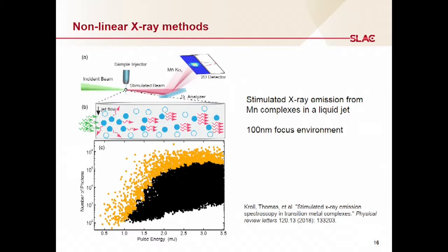At some point, they actually see saturation, which means that they are no longer able to excite any more particles because all of the particles have been excited past what they can already handle. That means all of these electrons have already been put into excited states. There are no more core hole electrons available, and this is what happens in a laser. So what they did is they used the SASE laser to create an X-ray laser using this very high power density.